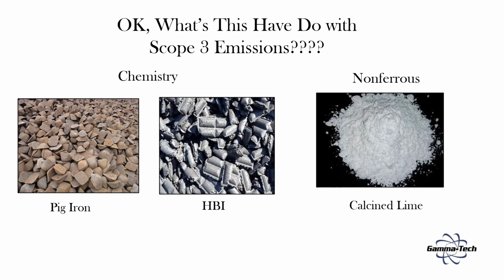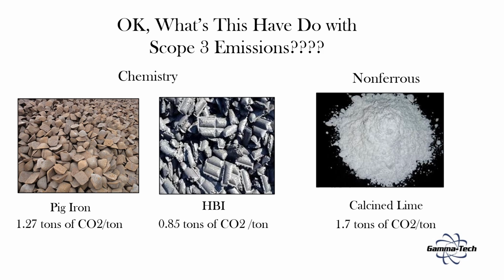That's the good news. The bad news is that each of those materials comes with a CO2 output, a scope 3 emissions associated with that. 1.2 tons per ton of pig iron, 0.85 tons of CO2 per ton of HBI, and 1.7 tons of CO2 per ton of burnt lime.